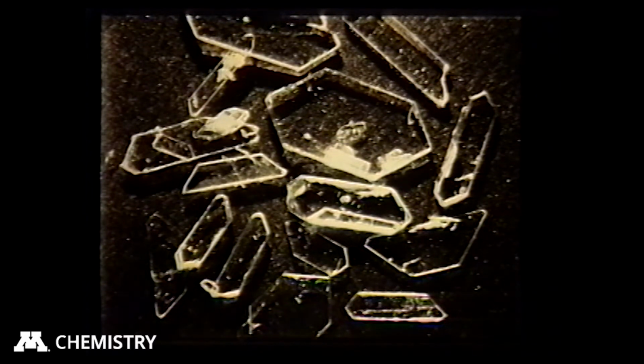And you get these crystals by crystallizing a methanol solution hot and cooling it fast. So these are kinetically favored crystals. They're not the stable form. The first form was the kind you get by slow evaporation, where you're more likely to get the thermodynamically stable form. So we think these are kinetically favored.